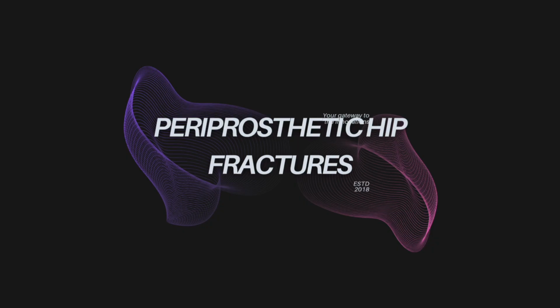Let's look at the mechanics of how these fractures actually occur. According to the German Arthroplasty Registry, intraoperative fractures occur 14 times more often around uncemented stems. Which makes perfect sense given the press-fit technique used to implant them. Exactly. You are wedging a titanium wedge into a rigid biological tube, the femur, until it's tight enough to hold. The fracture happens precisely during broaching or implantation, meaning the mechanical force of the titanium wedge causes the bone to crack to relieve the pressure. The bone-implant interface is inherently volatile at that exact moment.